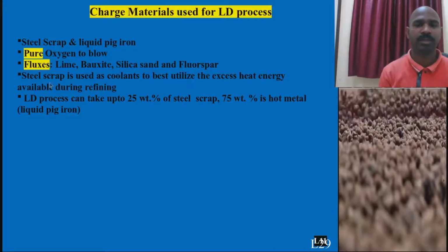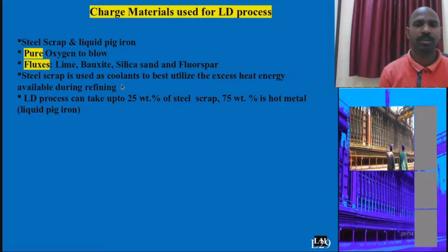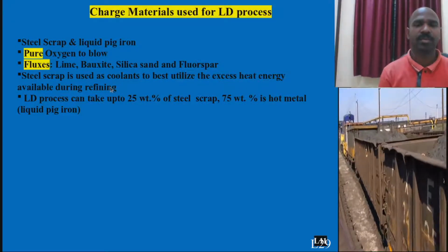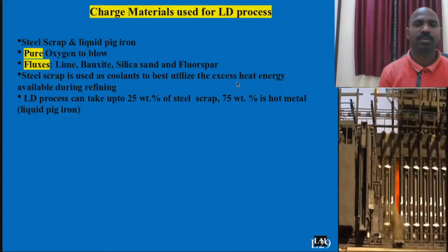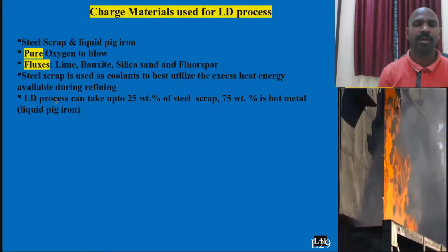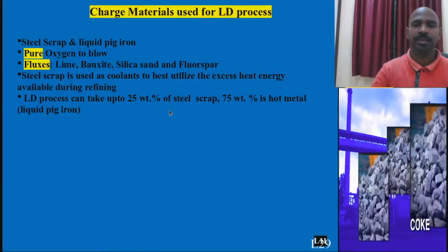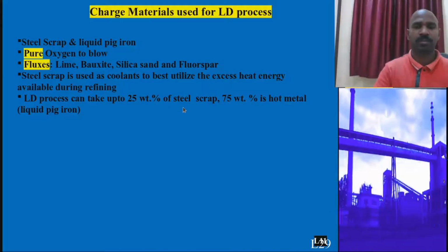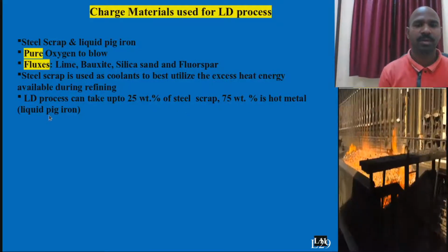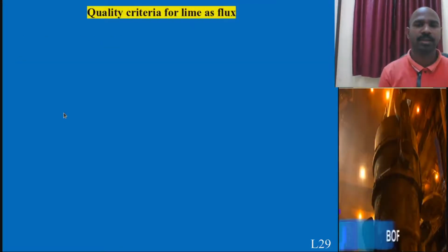One needs to notice that steel scrap acts as a coolant, balancing the heat energy so that it does not go so high in the chemical reactions. The LD process can accommodate steel scrap up to a maximum of 25%, and the remaining is hot metal, which is nothing but liquid pig iron. Please make a note.